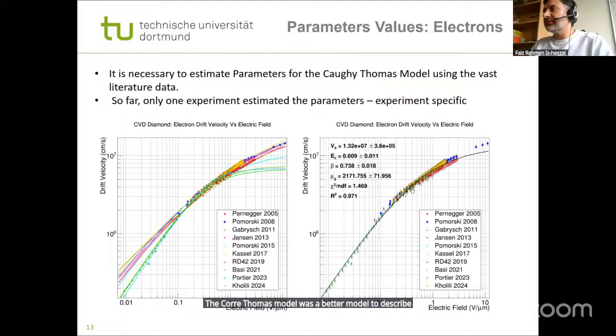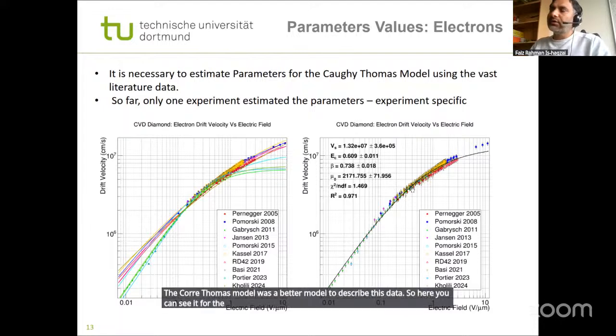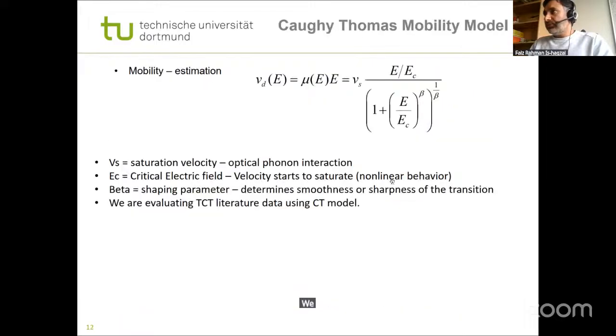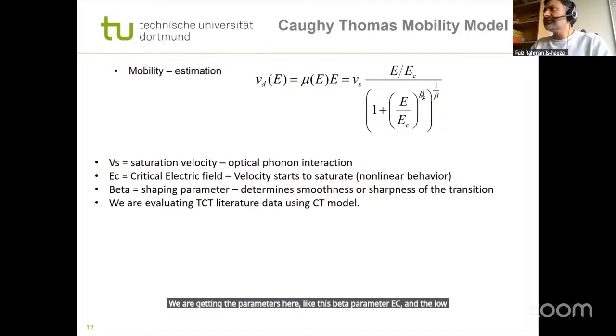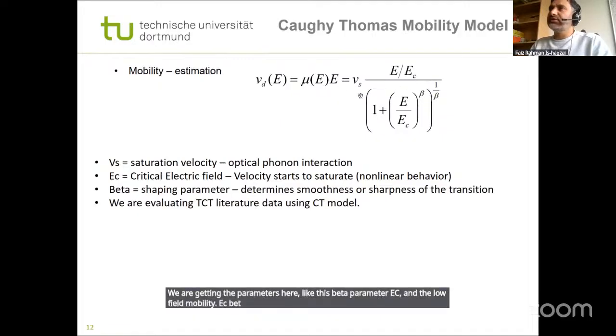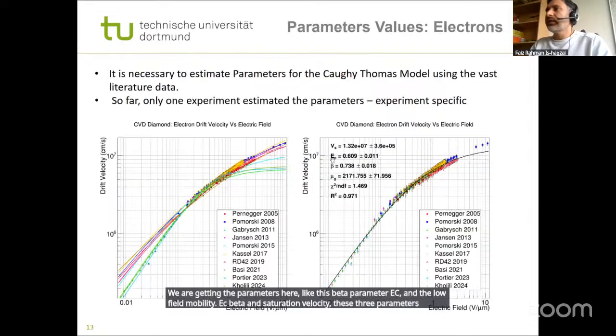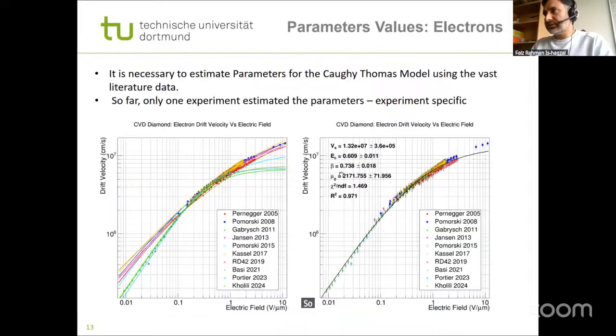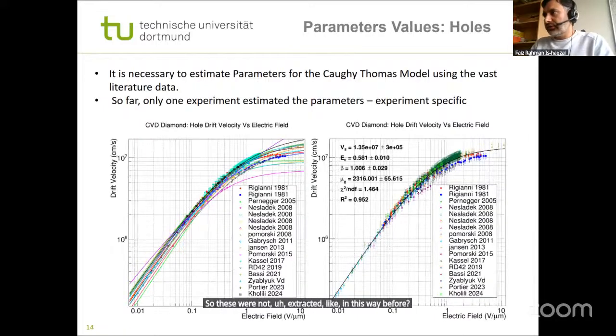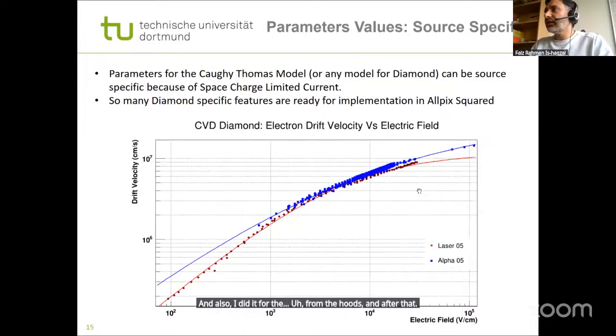Here you can see it for electrons. We are getting the parameters here: the beta parameter, the critical field EC, and the low-field mobility. These three parameters we got, EC, beta, and saturation velocity, and these had not been extracted in this way before. I also did it for holes.